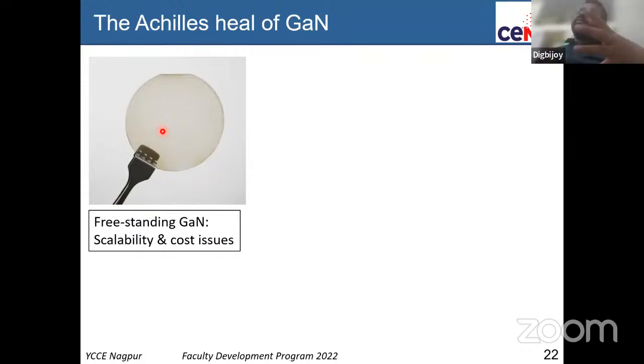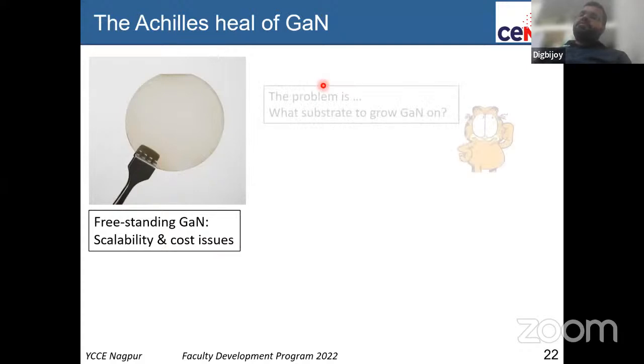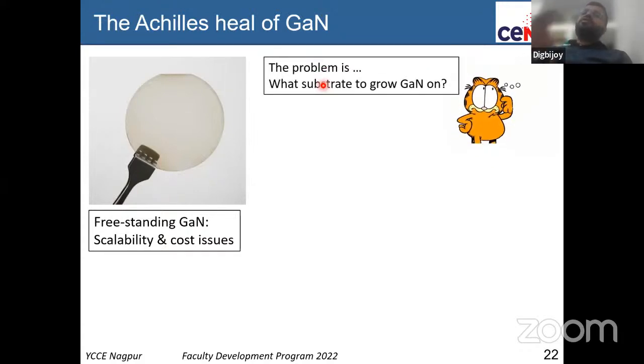Now, making large area gallium nitride wafer, as I told you, is prohibitively expensive. It's also technically very, very difficult, probably impossible to make 6-inch, 8-inch. There's material issues. It's not the same material as silicon. You cannot do bulk growth. All these issues are coming up. So the solution is to grow gallium nitride on a different substrate.